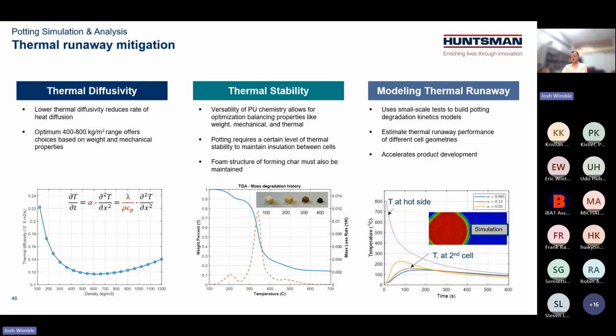So in some cases, adjacent cells may be overheated from ambient temperature of the cell that's going through the thermal event, through the incident, before the flame even touches it. And so that might set off the adjacent cells before the flame is even necessarily a factor. So insulating that heat, isolating it to this particular area is key, as well as thermal stability. So you want these potting resins to form char, but also maintain their structure. So the quicker the resin wears away, the worse that typically is for thermal runaway mitigation. Now, our resins typically aim to achieve less than 0.5% reduction in weight by the time it's reached 250 degrees Celsius sustained.